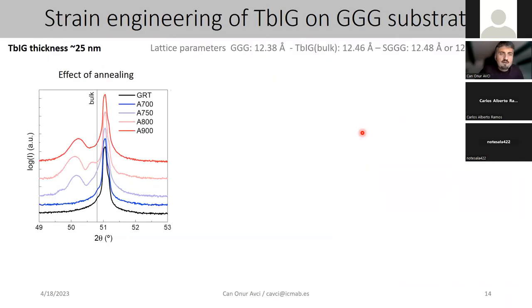So as customary in any kind of material development, we started by growing some terbium iron garnet on typical GGG substrates, first at room temperature. And as you can see from this 2θ-ω scan, XRD scans of the films, you see that these large peaks correspond to the substrate, and this line